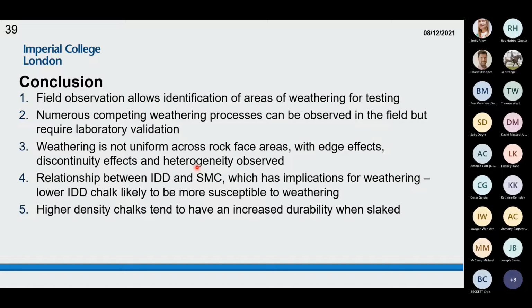Sorry, lower intact dry density is likely to be more susceptible to weathering, whereas high density chalks are likely to be more durable and also less susceptible. High density chalks also tend to have an increased durability when slaked, which would indicate that in the field these are less likely to be weathered due to wetting and drying cycles than a younger chalk is likely to be.